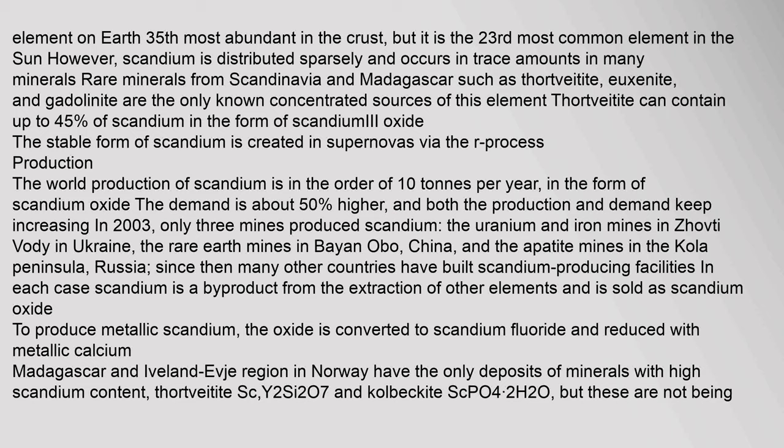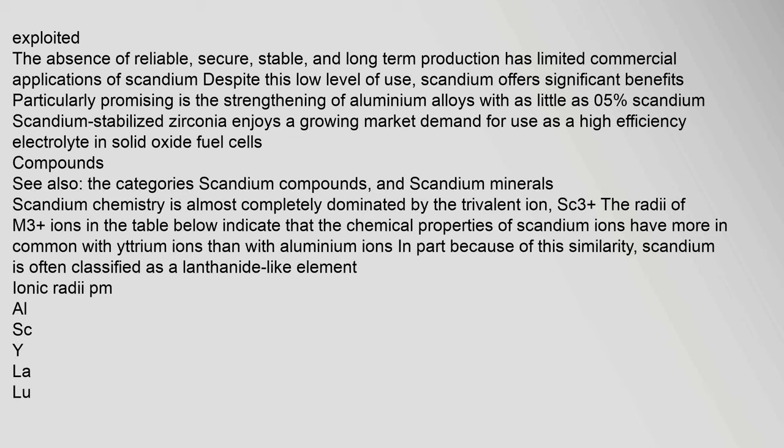In each case, scandium is a byproduct from the extraction of other elements and is sold as scandium oxide. To produce metallic scandium, the oxide is converted to scandium fluoride and reduced with metallic calcium. Madagascar and the Iveland-Evje region in Norway have the only deposits of minerals with high scandium content — thortveitite and kolbeckite — but these are not being exploited. The absence of reliable, secure, stable, and long-term production has limited commercial applications of scandium. Despite this, scandium offers significant benefits, particularly the strengthening of aluminium alloys with as little as 0.5% scandium.